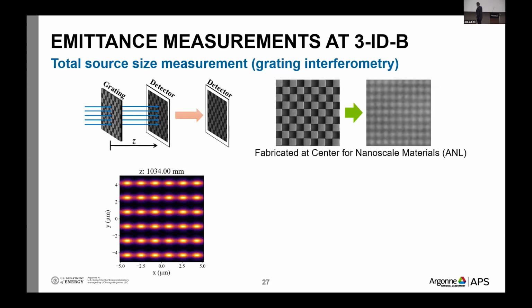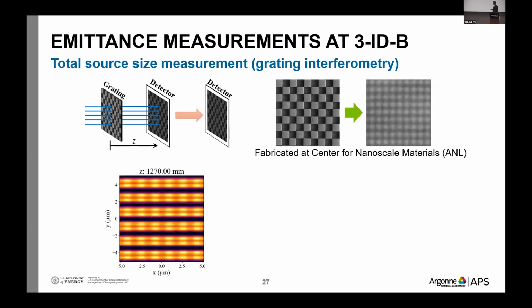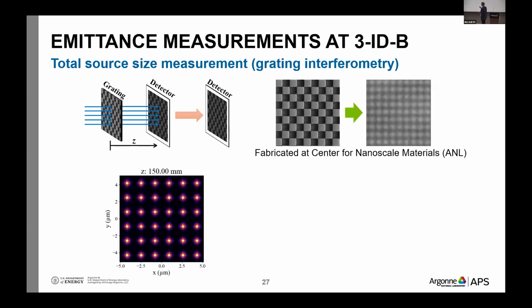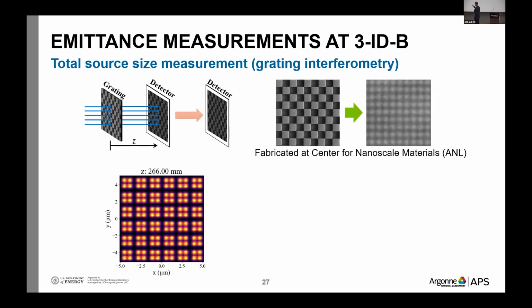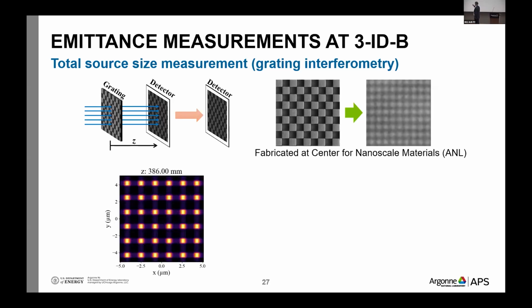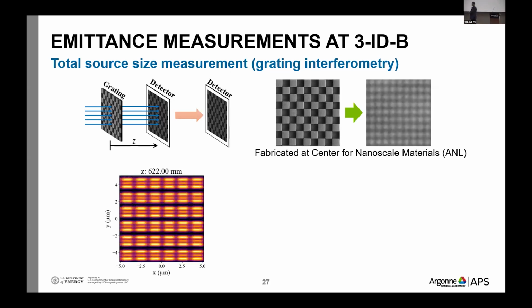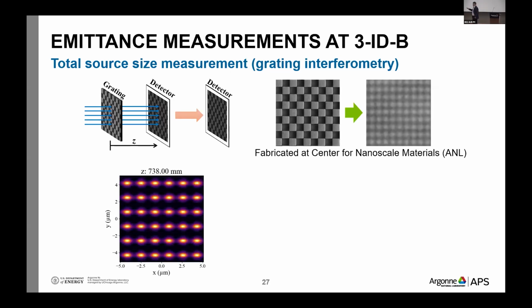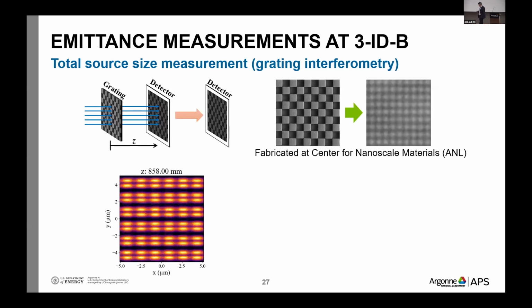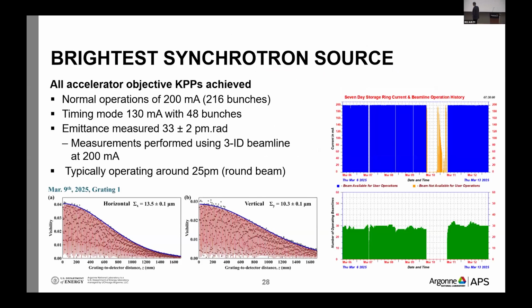And this was the very first measurement, which is also a good story in its own right, because I think the measurement is beautiful, but also the gratings were actually prepared at CNM. So in the context of the APS CNM meeting, that's a good thing. This is a gold square pattern deposited on silicon nitride, and you use this grating to produce a self-image of the beam, and you move the detector further away from the grating, and you measure this self-imaging effect as a function of the distance from the grating. And you see some very nice interference, which essentially enables you to measure the size of the beam, and eventually from the size and machine parameters, you can go back to the emittance. So this was done relatively early on, a beautiful measurement.